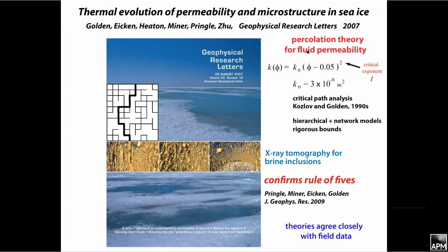And then also we developed a beautiful multifaceted theory of the fluid permeability in sea ice. Here's the 5%. There's the best known value for the critical exponent that describes the takeoff of the permeability. And then here's a factor in front, which is interesting. This is not a fudge factor that we fit to the data. It's actually something that we predict from our X-ray tomography and a very interesting theory called critical path analysis that says for fluid flow or electrical flow, bottlenecks control the flow.